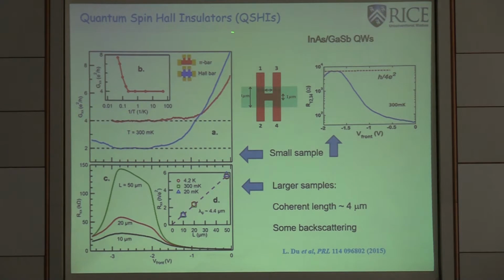So this is the region where we observe the quantum spin Hall effect. The signature for this, of course, is the quantized edge transport. In small devices, these devices typically have a size of 2 micron. Now, if your sample is less than 2 micron, you are able to see the quantized edge transport. Depending on how you connect to the device, this is a 6-terminal device. This is a 4-terminal device, and according to the Büttiker formula, you will get a different number of quantization. So this is 4e squared divided by h. This is 2e squared divided by h.